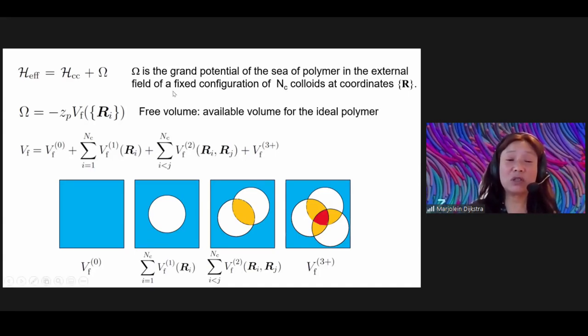And this grand potential for this very simple system can also be seen as minus the fugacity of the polymer times the free volume, and the free volume is just the available volume for the ideal polymer. And the available volume can be split into a zero-body term, a one-body term, a two-body term, and a three-body term. The zero-body term is just the volume that is available for the polymers when there are no colloids present. The one-body term is just the volume that is excluded by each colloid. And then you overestimate it, and that is corrected by the two-body term. The zero, the one, and the two-body terms are known analytically.